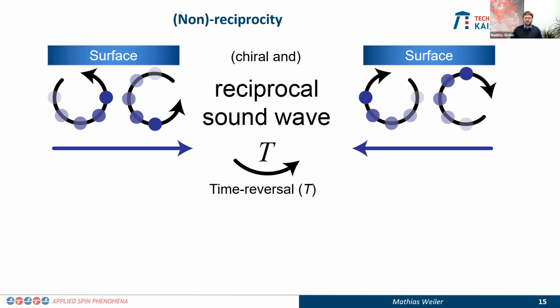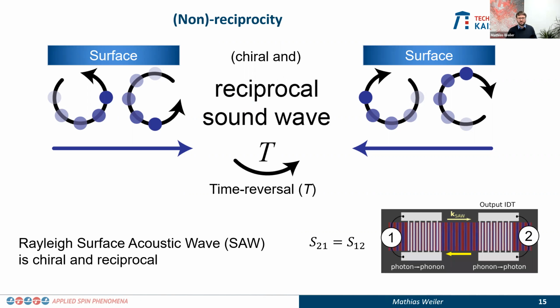And that doesn't change if you introduce a surface. So surface acoustic waves are actually chiral objects that are reciprocal. And that means if you have two individual transducers and you send an acoustic wave from one side to the other or this side, you will obtain the same transmission. And that's what one typically does in these experiments over here. So Rayleigh waves are chiral, but they are reciprocal.